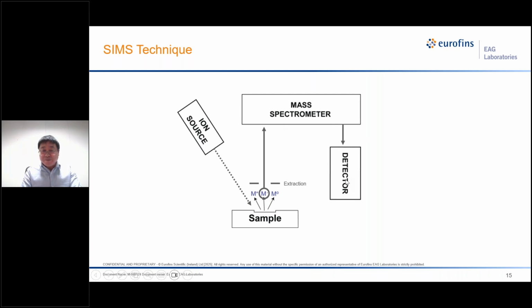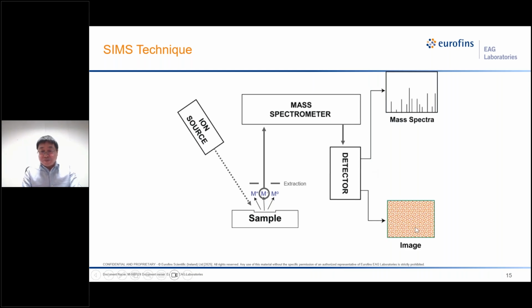negative species as an example. The negative species are extracted from the sample and go through the mass spectrometer, then enter the detector. Depending on the mode, we can scan the mass depending on their mass over charge ratio, and we can get the full spectrum. Or we can raster the primary beam to get an XY image of the sample. Or we can select one mass or several masses to get the depth profile.